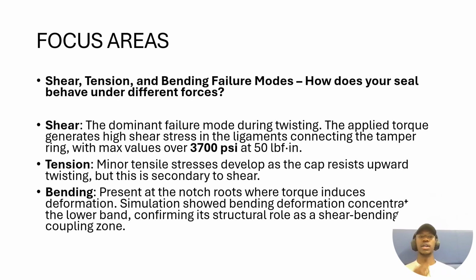My other focus areas were about shear, tension, and bending failure modes, and I wanted to find how my seal behaves under different forces. I found out that shear dominates the whole failure mode, because when you apply torque, it generates a high shear stress in the ligaments that are connected to the tamper ring, and the max values were over 3,700 psi at 50 pound-force inches, which is a lot. Tension and bending also occurred, but they were very minor stresses. They were just secondary, not really primary to the whole objective of the design.